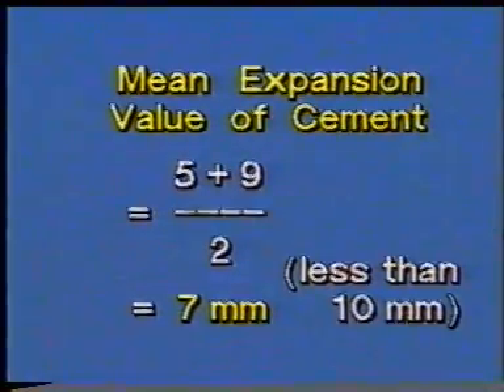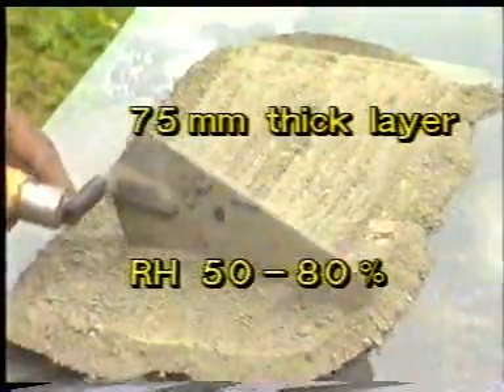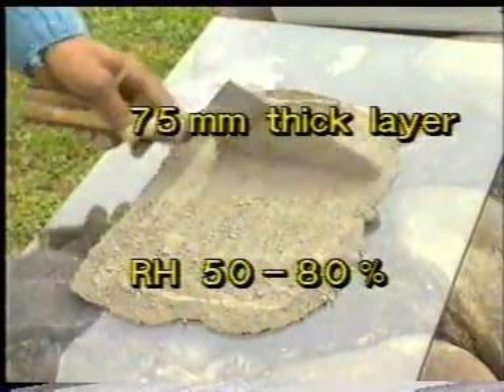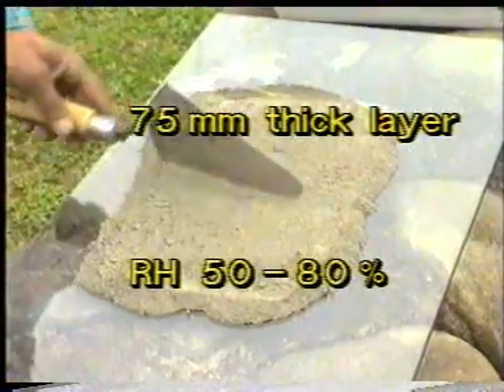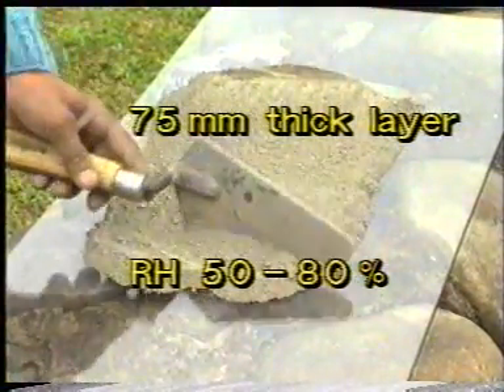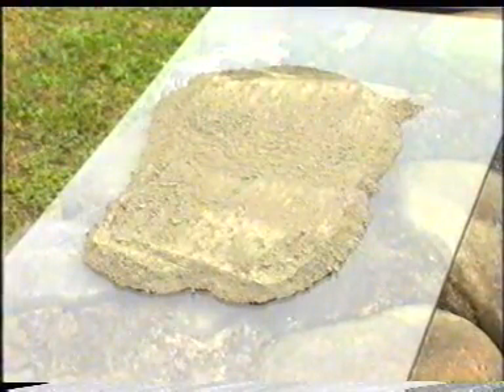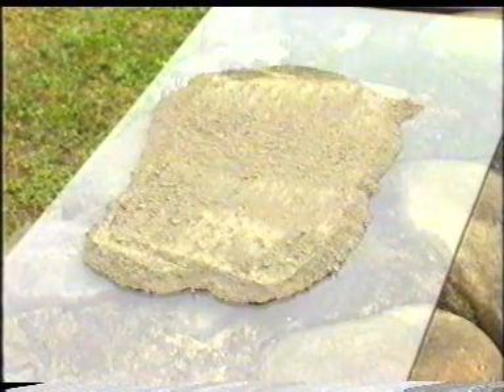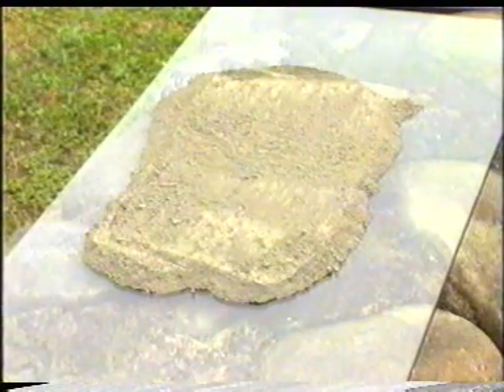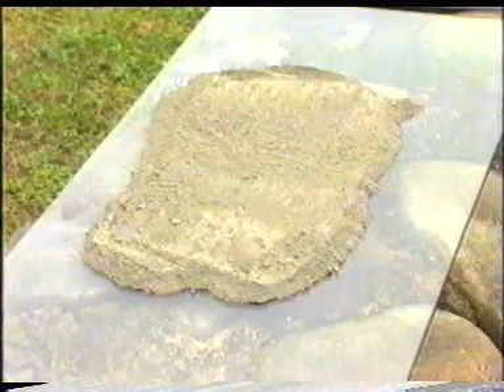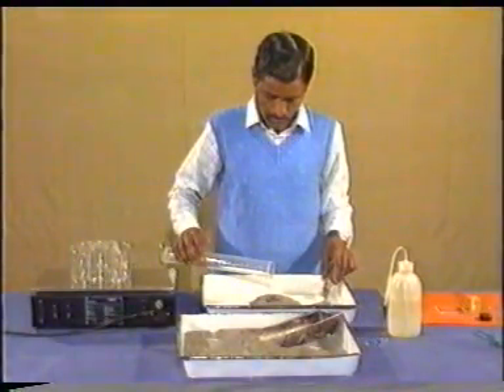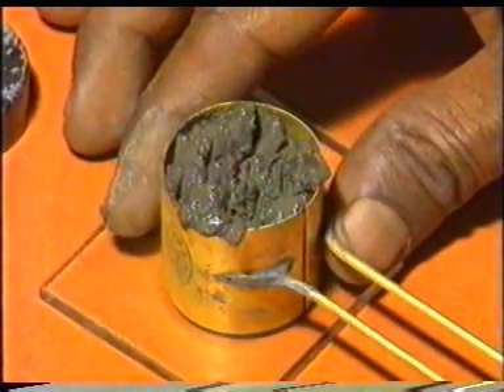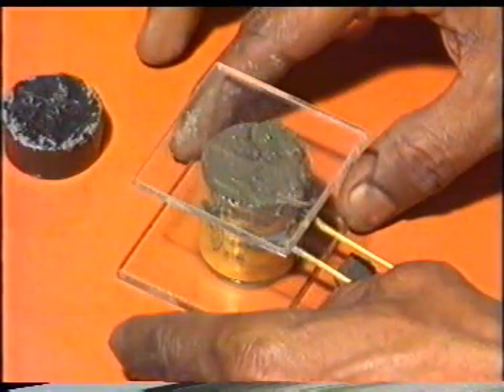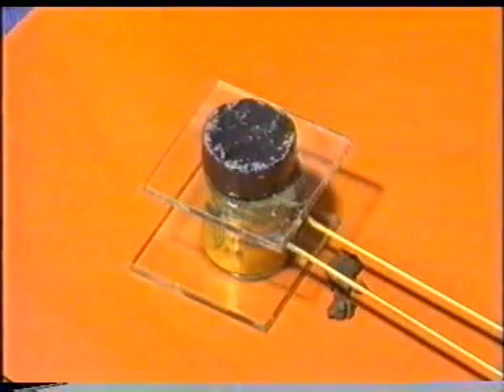In the case of unsound cement, the aerated cement test is carried out, which involves spreading out the cement in a 75 mm thick layer in an atmosphere of relative humidity of 50 to 80%, maintaining a temperature of 27 plus or minus 3 degrees Celsius and keeping it for 7 days. Retest this aerated cement sample.